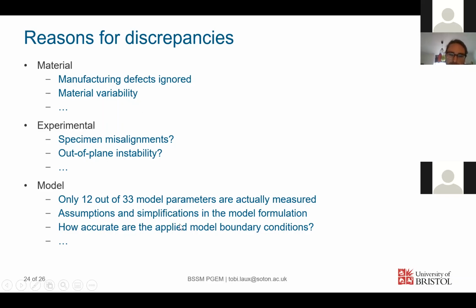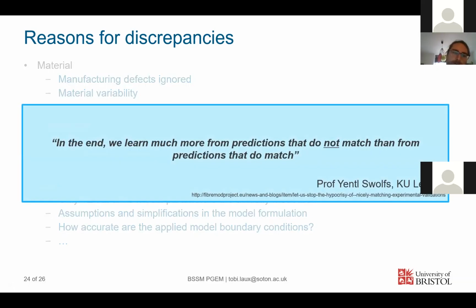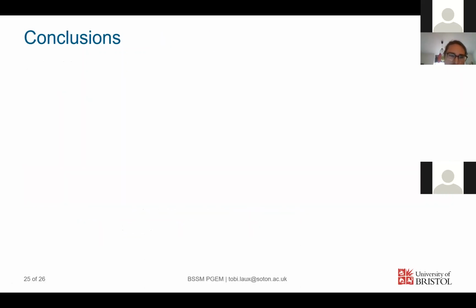We have certain assumptions and simplifications in the model, of course, and also the accuracy of the boundary conditions could be an issue. But I think a very important fact is that in the end, we learn much more from predictions that do not match than from predictions that do match. That's something Yentl Swolfs, not sure if I pronounced this correctly, said recently, and I think it's really very true. And whenever you are in a validation process between model and experimental results, I think this is something to keep in mind instead of going crazy to try to get your models to match the experimental result.